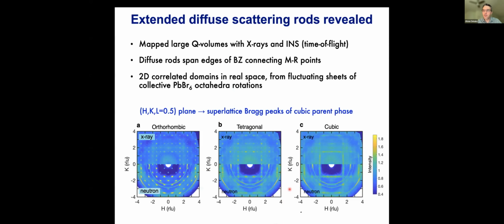Okay, so if we have rods in reciprocal space, this indicates we have two-dimensional correlations in the disorder away from the average crystal structure in real space. However, from the diffuse scattering, we don't know, because this is energy integrated at this point, whether this is static or dynamic. And so I'll show you these are actually fluctuating deviations from the average crystal structure corresponding to correlated or collective lead-bromine octahedral rotations.